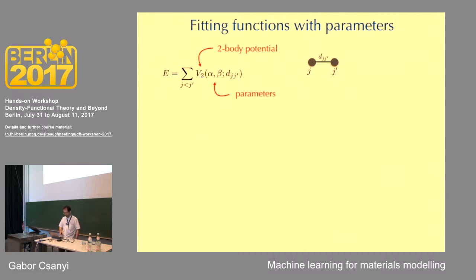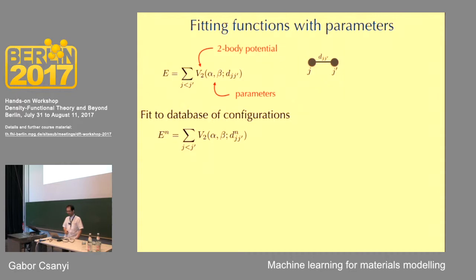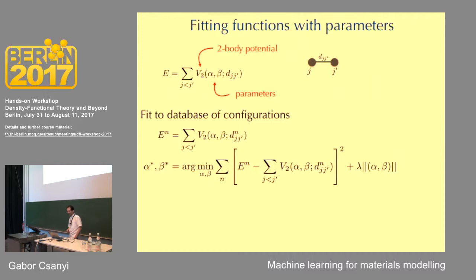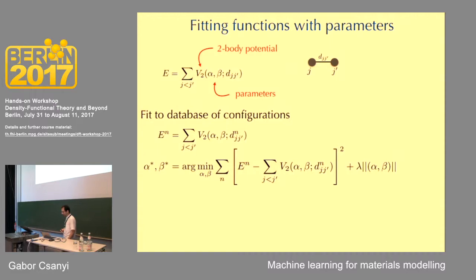To get more mathematical: the way to fit a simple function like a pair potential is to write the total energy as a sum of a function V2 with parameters α and β depending on distances between atoms, summed over all pairs. Given a few example configurations with DFT total energies, you write equations with the total energies on the left and your ansatz on the right, and you find the α and β that minimize the squared difference. You may want to regularize, choosing the solution with the smallest norm, among those that achieve the minimum.